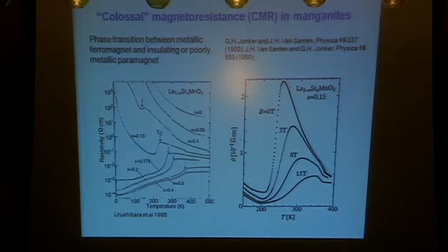Manganites. Many of you will know this. I'll do this very briefly. The history of manganites, of course, goes back a long time to the 50s, but was resurrected in the mid-90s with the discovery of what became called colossal magnetoresistance. But this is nothing more than systems like lanthanum manganite doped with holes by replacing lanthanum by strontium, whereby you go from a material, which is resistivity versus temperature on a log scale, which is a very sound insulator, to something which has a transition temperature here, marked TC, which is actually ferromagnetism, and into a low temperature phase, which is a metal. And as you can see, there's a correlation here between there being metallic ferromagnetism and sort of a bad metal phase above TC.